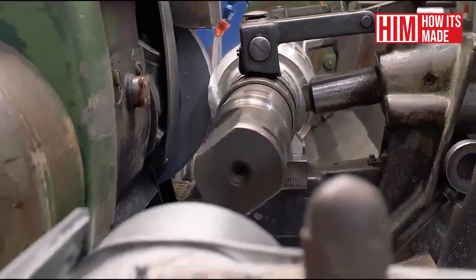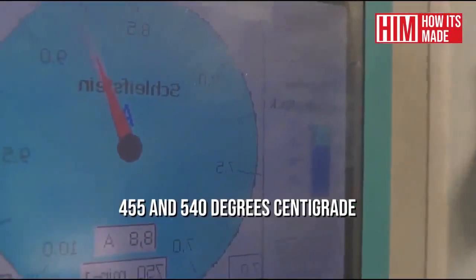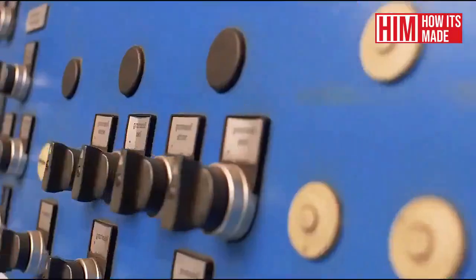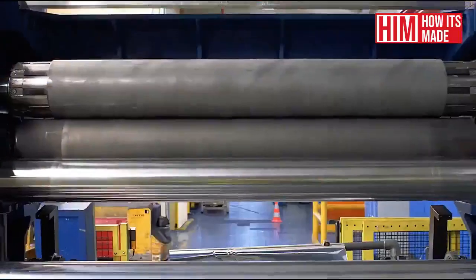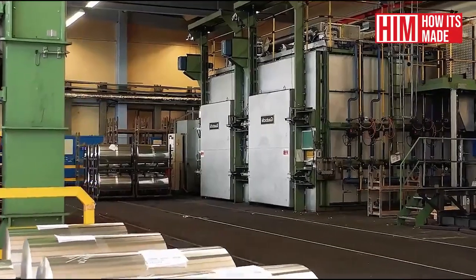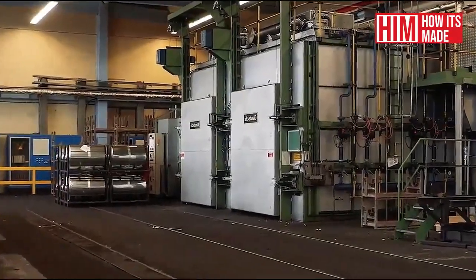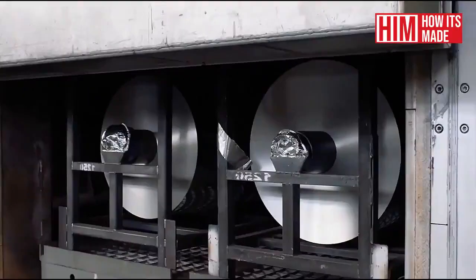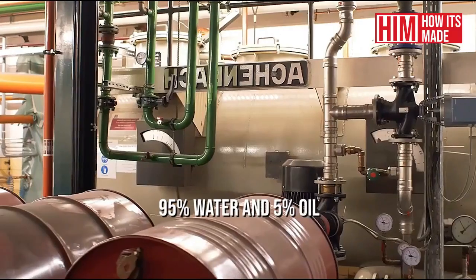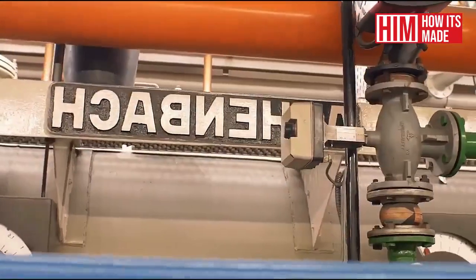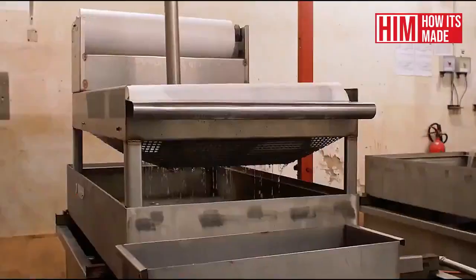Temperatures inside the rollers are between 455 and 540 degrees centigrade, and pressure on the ingot is continually verified by a professional technician. If the temperature exceeds that, it's lowered by the technician, who then adjusts the pressure. The heat is so high that the ingot risks sticking to the mill's roller. To prevent this from happening, everything is cooled with a liquid that is 95% water and 5% oil. This helps keep the roller from becoming sticky and sends the ingot further.